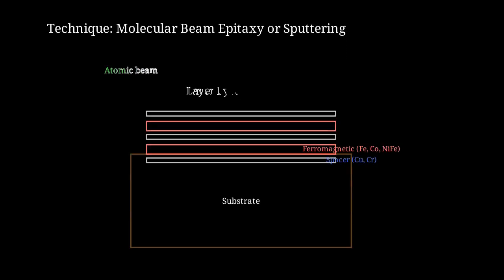The most common fabrication techniques are molecular beam epitaxy, or MBE, and magnetron sputtering. These allow atomic layer precision in depositing materials. Here's a schematic of the fabrication process. We start with a substrate, typically silicon or glass. Using MBE, or sputtering, we deposit layers one atomic plane at a time.